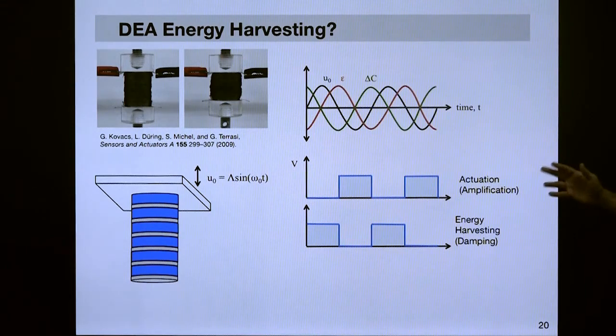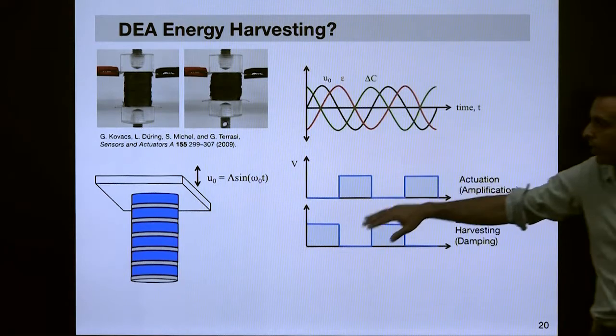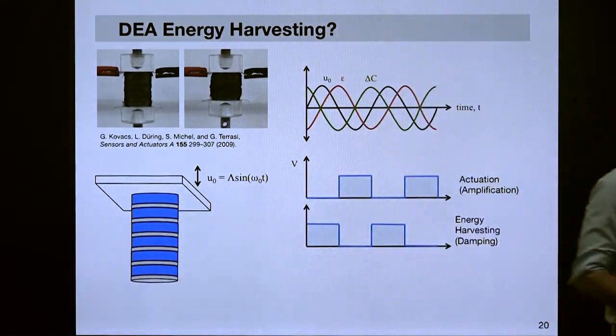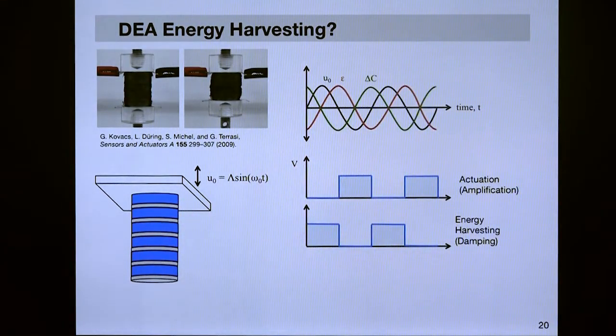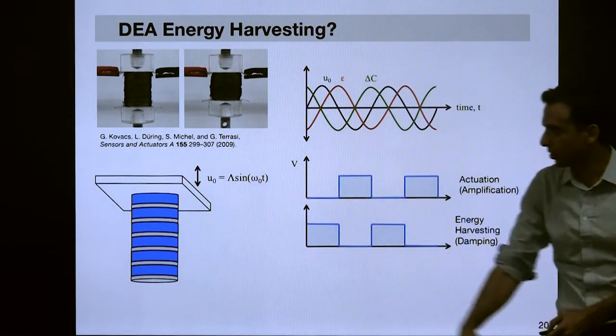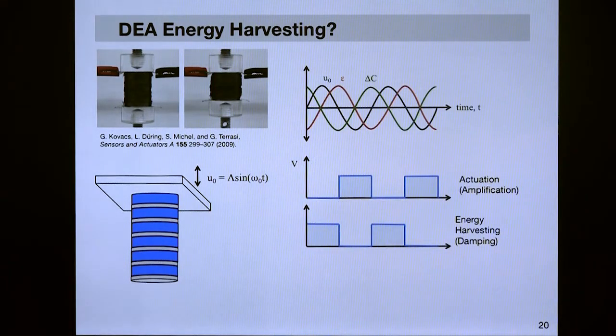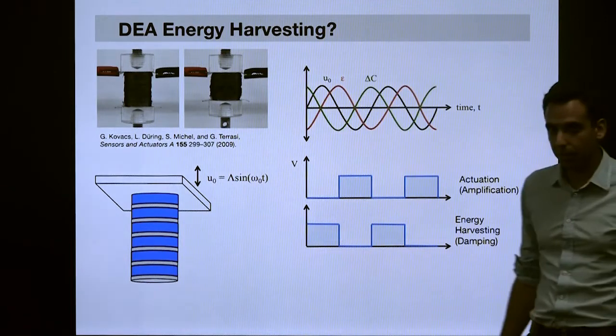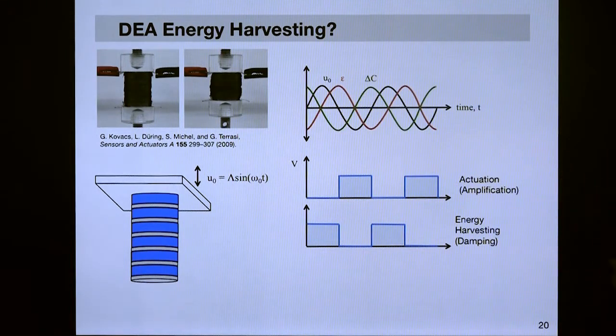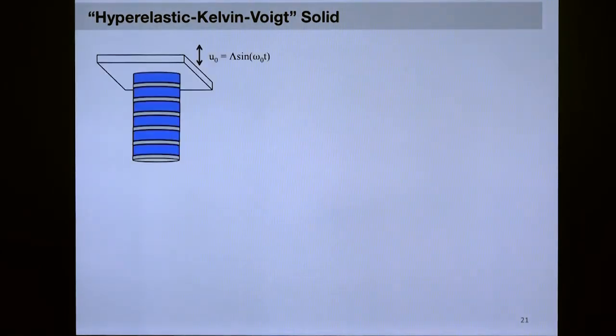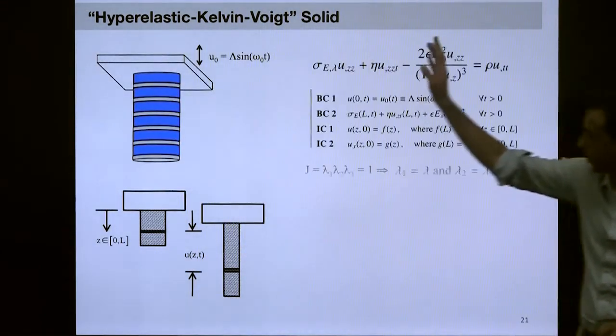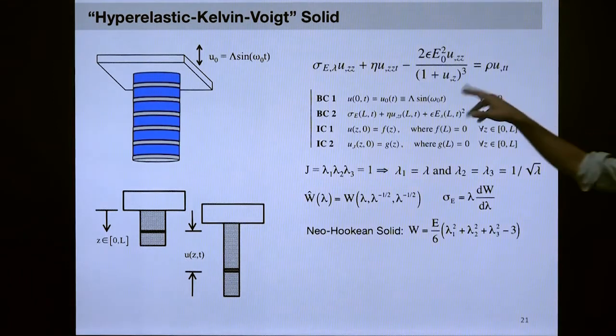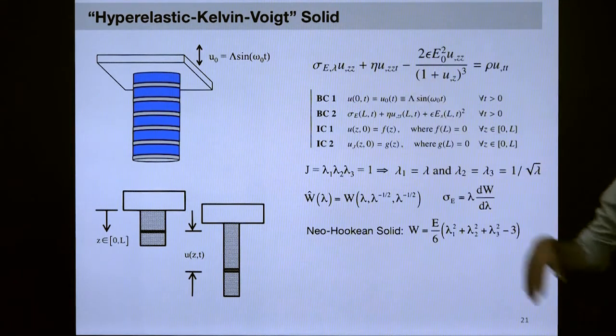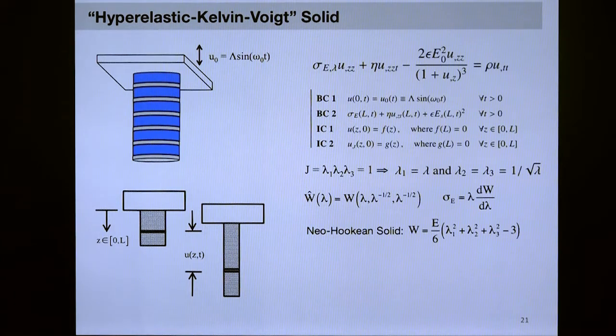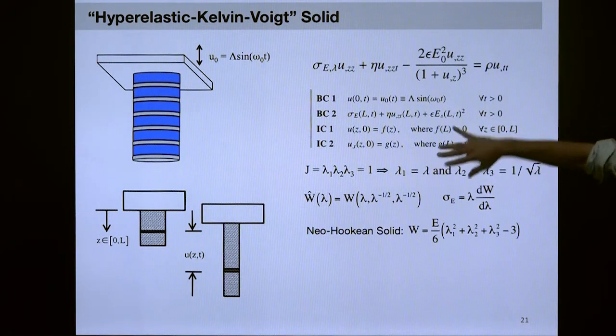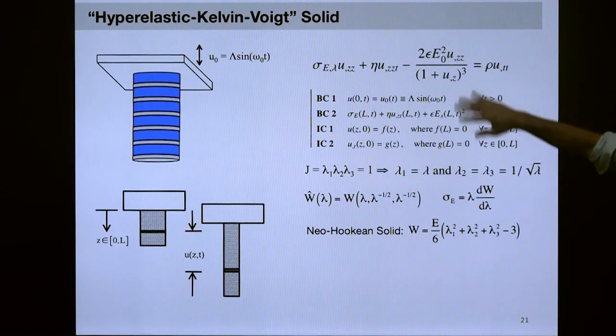But that damping energy has to go somewhere. It goes into the voltage stored in the charges inside those capacitive elements. We can then take those charges with that heightened voltage and extract that energy as electrostatic energy. So in that mode, we can use this for energy harvesting. Then we can draw free body diagrams and derive the governing PDEs. I'm using a shorthand, Einstein-type notation to represent the PDEs, and we have all our boundary conditions. We can plug in pretty much whatever strain energy density we want.